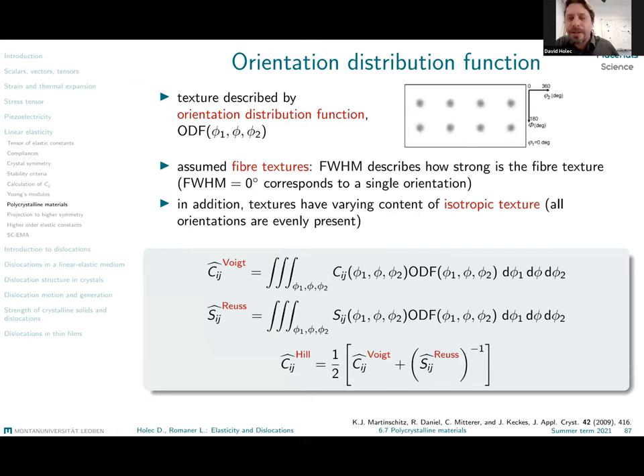So for the elastic or isotropic aggregates on the previous slide, the ODF is simply a uniform function for each orientation given by the three Euler angles, phi 1, phi, and phi 2, so the crystalline orientation of my single crystal with respect to the laboratory system. I would have the same probability, right? So the ODF would be a uniform function. If I do not have a uniform function and I have certain preference for some orientations, I do get peaks there. And of course, then that would give more weight to those elastic responses.